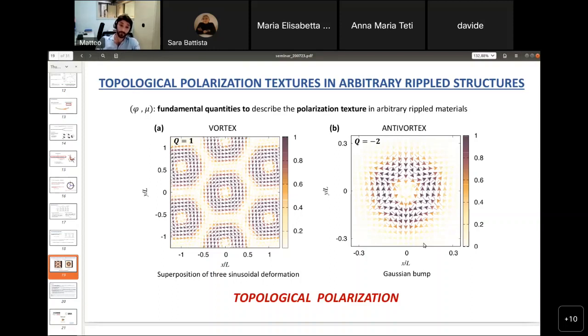In particular, we find that the polarization field is not trivial at all. And indeed, for example, in the first case, we find that the resulting field corresponds to a honeycomb lattice of vortices. And the second one corresponds to this strange figure, where both of them are non-trivial figures, but they can actually be described. They are actually specific topological figures. The first one is the so-called vortex that is described by a characteristic topological number, the so-called winding number, and in particular by a winding number equal to 1. And the second one is a so-called anti-vortex described by a winding number equal to -2.